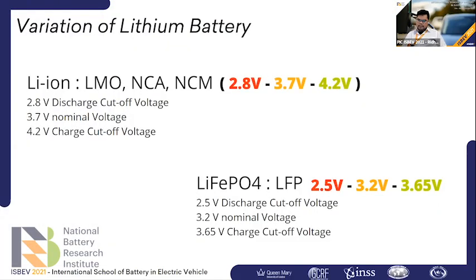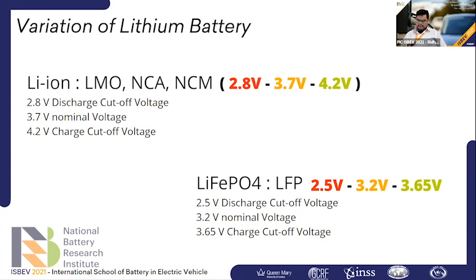We also need to know the characteristics of each battery type. We divide them into two variations: lithium-ion and lithium iron phosphate. Lithium-ion, which can be NCA or NCM, has a nominal voltage of 3.7 volts, a discharge cutoff of 2.8 volts, and a charge cutoff voltage of 4.2 volts. It has higher energy density compared to other materials.